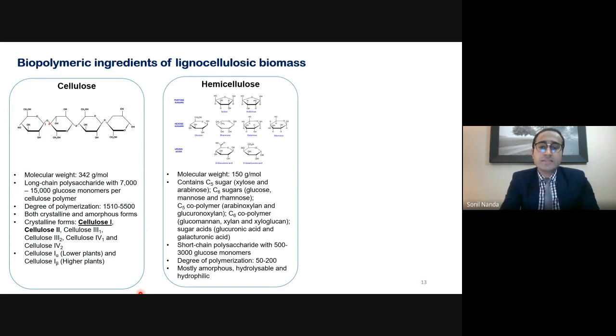Now, hemicellulose is not a crystalline sugar, but it's an amorphous material, and it contains both sugars and sugar acids. Hemicellulose comprises pentose sugars or C5 sugars like xylose and arabinose. It also contains hexose sugars like glucose, rhamnose, galactose, and mannose. These are all the C6 sugars. And hemicellulose also contains sugar acids like glucuronic acid and galacturonic acid. So it's a heteropolysaccharide. Now, the molecular weight of hemicellulose is relatively lower than that of cellulose, as you can notice here. And also, hemicellulose is a short chain polysaccharide comprising 500 to 3,000 glucose monomers, unlike the cellulose, as you can see here.